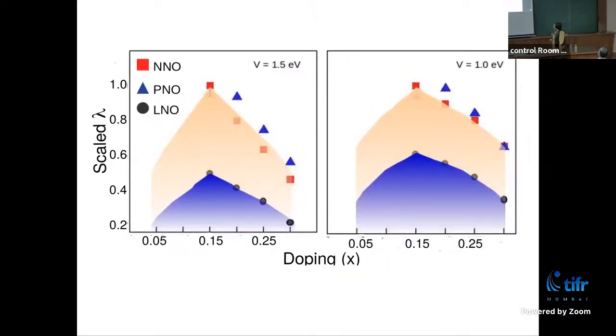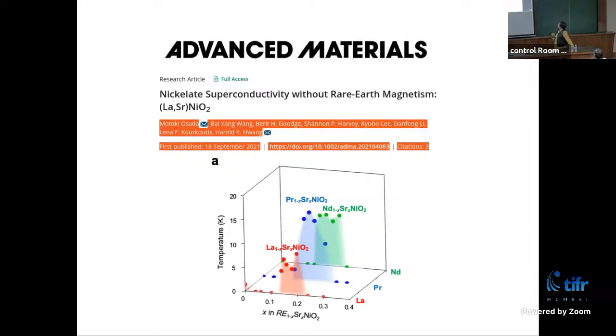And with that, we actually computed the doping dependence. We could not really go to the low doping because there our theory will fail. So that's basically our construction. So you find for neodymium and praseodymium, we expect the TC to be similar, while for lanthanum, it will be strongly suppressed. When we published our paper, there were no experiments on lanthanum because they could not make the lanthanum superconducting. But after our paper, there came the phase diagram from the same Harold Hwang group, maybe they got motivated by us, for praseodymium, neodymium, and lanthanum. Exactly, the TC of praseodymium and neodymium are very similar, while for lanthanum, it is suppressed by about a factor of 2, which was also our prediction.